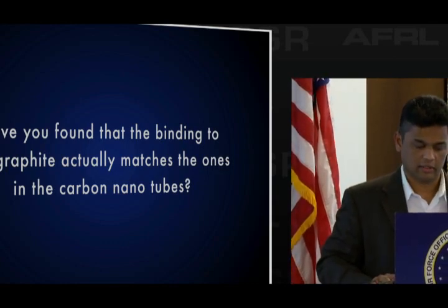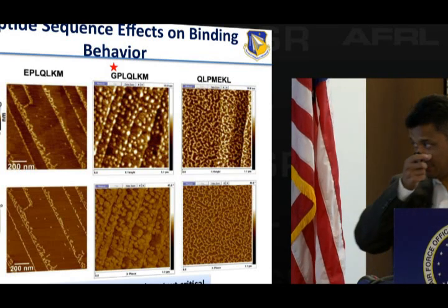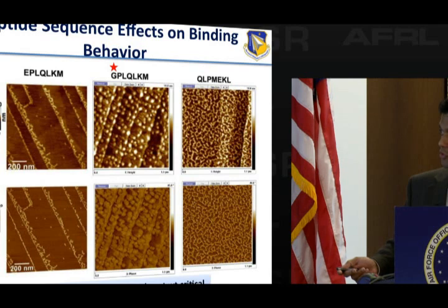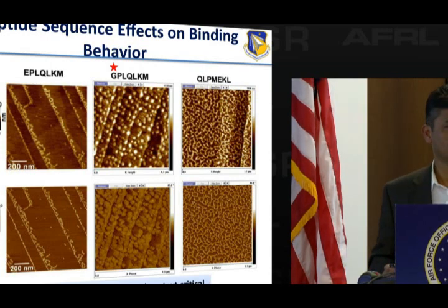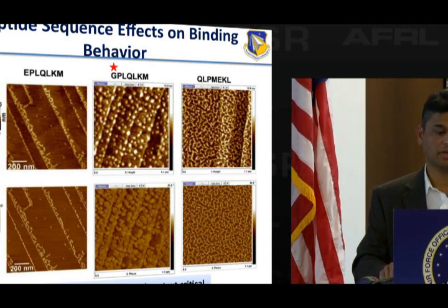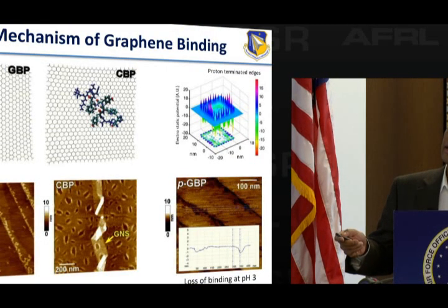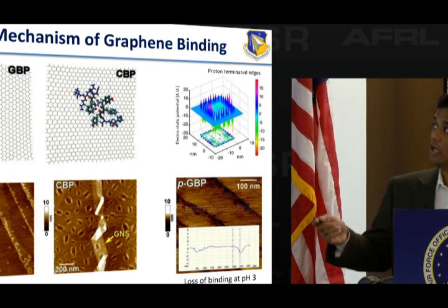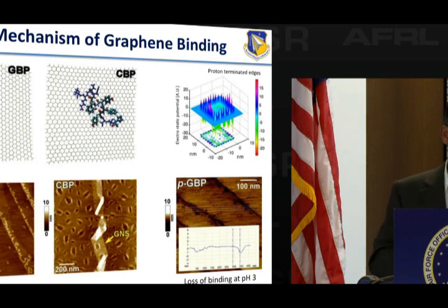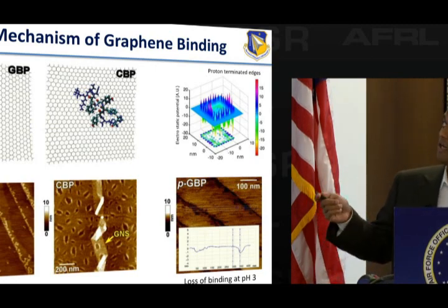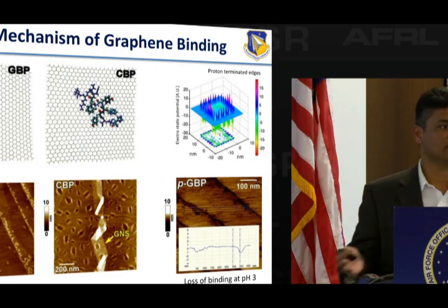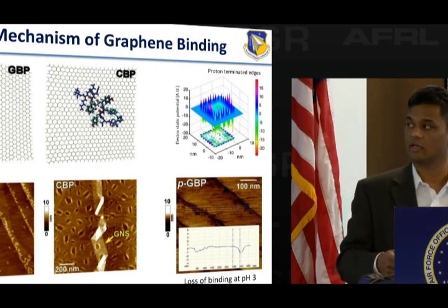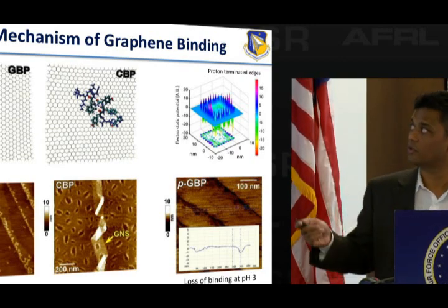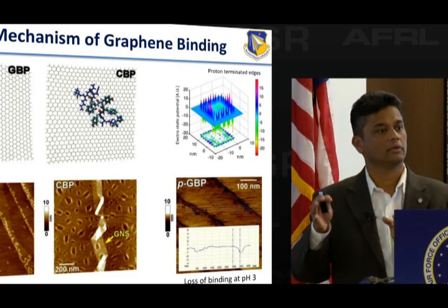So let me go back, bear with me for a minute. This is a carbon nanotube binding peptide, okay? What I've shown here are aromatic residues, and I've shown you the polar residues in black. So you can see very distinct blocks, but this one domain is hydrophobic, and that's how it interacts with the carbon nanotube surface. Now, if I go to the graphene binding peptide, this is hydrophilic, this is hydrophobic, this is hydrophobic, this is hydrophilic, hydrophilic charged, hydrophilic, okay? Very different arrangement. When I make this mutation, I am creating this end to be hydrophobic. We did not think this was what was happening. And you can see that the architecture is completely different. It actually looks more similar to how the carbon nanotube binder is, because you have more of a planar surface. So it is where you have distinct domains of hydrophobic and hydrophilic amino acids that drives the interaction.